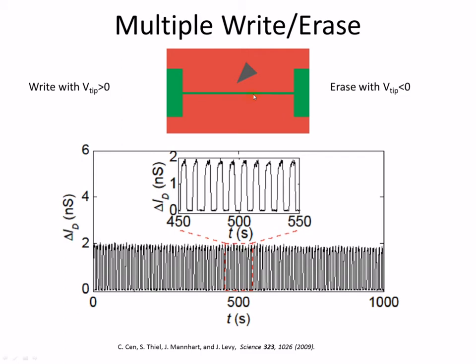As I was saying before, we can write and erase. In fact, we can do this multiple times. So in some sense, this is the analog of the experiment that was done in the Augsburg group, where they were able to switch repeatedly the interface between conducting and insulating. However, we're doing it over a very small area, and we can do it hundreds of times without any problems. So this is a rewritable interface at the nanoscale with feature sizes that are in each direction about 1 million times smaller than the Etch-a-Sketch. So the dot size is about 1 trillion times smaller than what you can achieve with an Etch-a-Sketch.